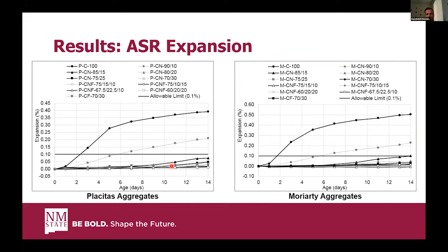As a result, first of all, we found that only 10% replacement of the cement with natural pozzolan is not adequate to reduce the ASR expansion below 0.1%, which is acceptable to many transportation agencies, for both types of the aggregates that we have used in this project, Placitas and Moriarty. But even in the Moriarty aggregate, in the right figure, we can see that mixtures with 15% replacement of the cement with natural pozzolan were not qualified for ASR expansion because the expansion was just marginal, about 0.1%.